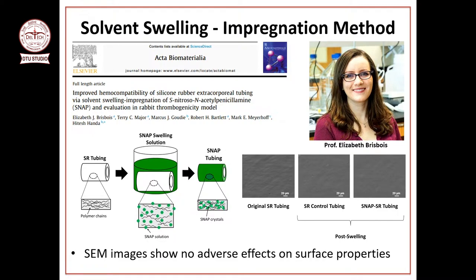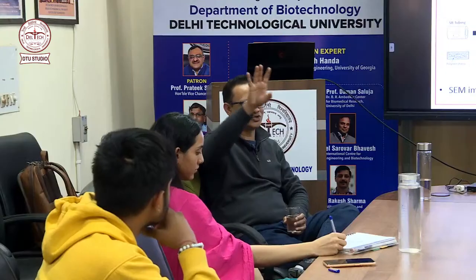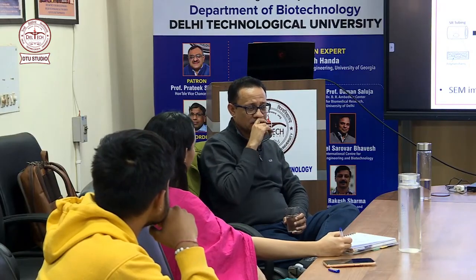So, NO donor molecules are very heat sensitive. But how do we extrude now? To make catheters and tubings, there is an extruder, where pellets of polymers are dissolving. You are putting NO donor in it at high temperature and it's forming into tubings or whatever. But we saw autoclave basically killed all the NO release because of high temperature.